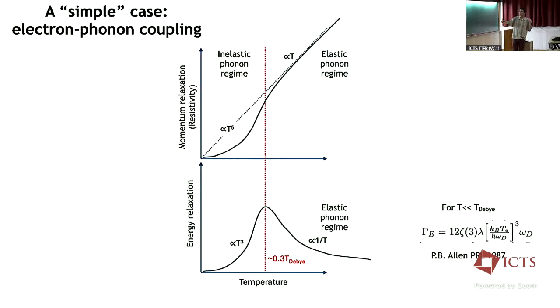This was first worked out by Phil Allen in 1987. I think that it's been used quite a bit for various kinds of optical pump experiments. And I'm not sure that it's really applicable to that case. Although there's been a lot of work done where you're pumping the system with 1.5 eV photons in a 1.5 eV laser. When you do that, you make this very, very high energy electron-hole pair. And the assumption is that there's this kind of fast decay back down to some very low energy scale. But I think that's an assumption which is not particularly justified. I think Allen's theory basically applies just directly to the kind of experiment we're doing, however.